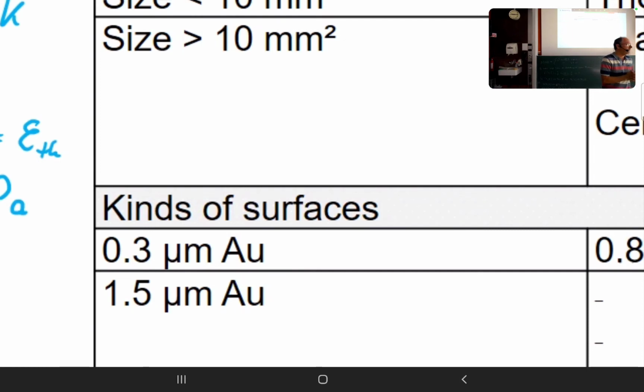factors for stress. Okay, so lead frame, for instance, if it's alloy 42 or Kovar, then we can stay below these 2.5 as a delta T. Also, when we use aluminum nitride, it's on the good side.